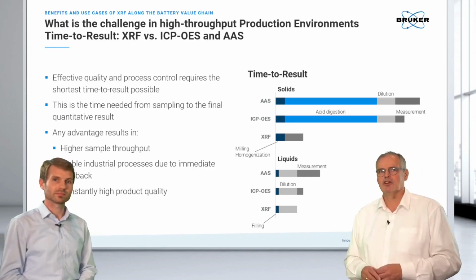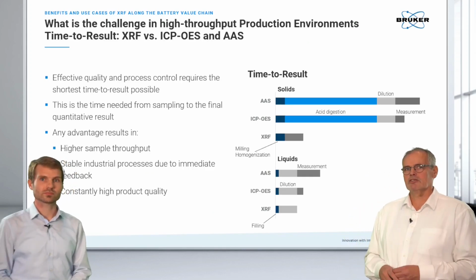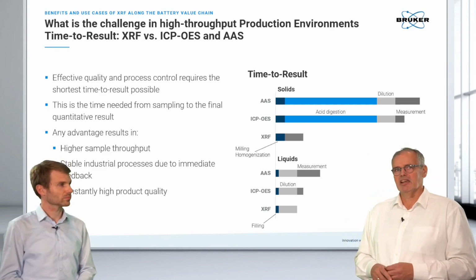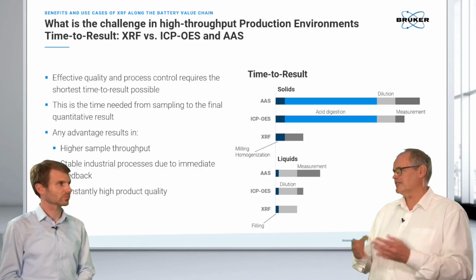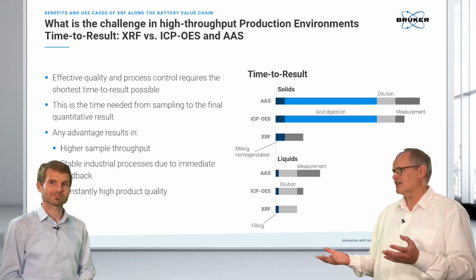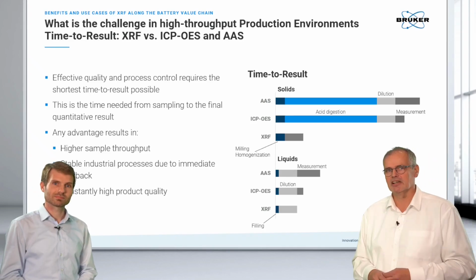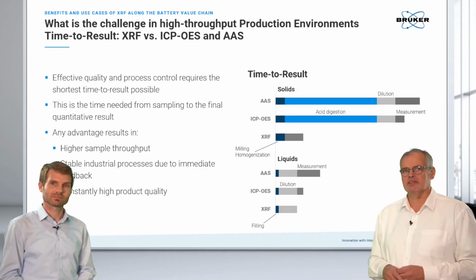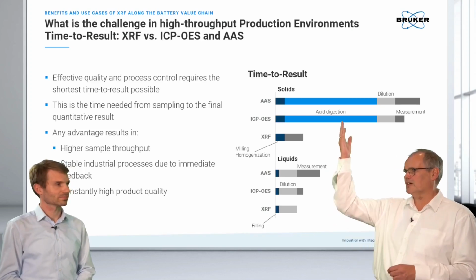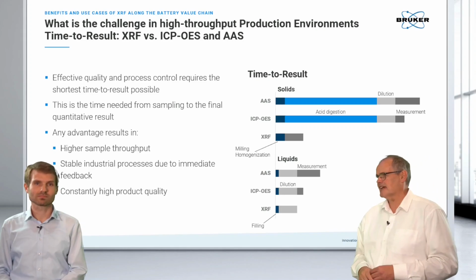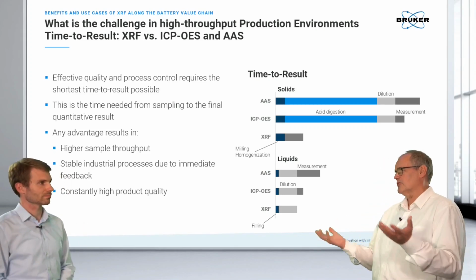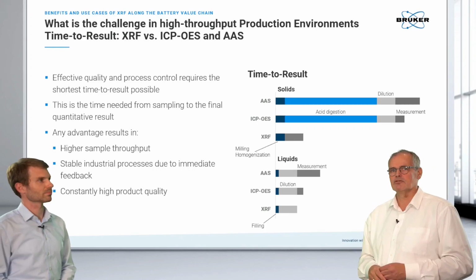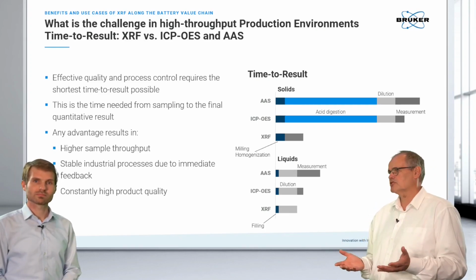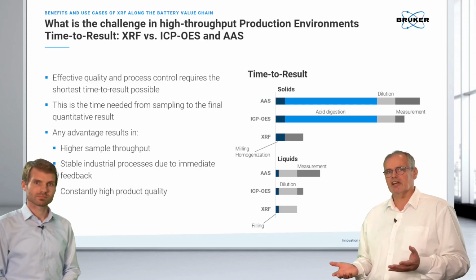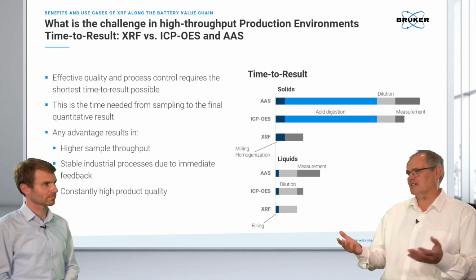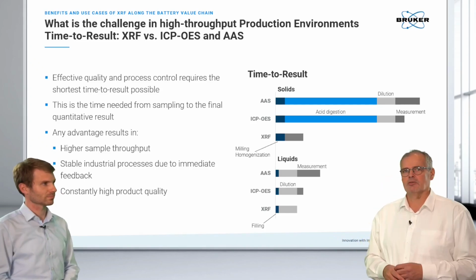Yeah, we have here a comparison actually. When you look into solids, we have learned that with XRF, we take the sample, we grind, we press it, and then we analyze it. A compact sample we can analyze directly. When we think about AAS or ICP mass spec, we see this long blue bar up here, and actually this is the acid digestion time. And then when we think about the cobalt or manganese solution, we have a high concentration. We need a dilution step. So therefore, we are spending a lot of time waiting for the sample to be finished. This takes easily a couple of hours in a normal workflow.